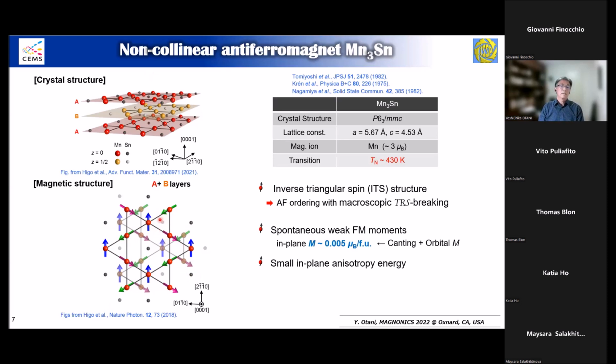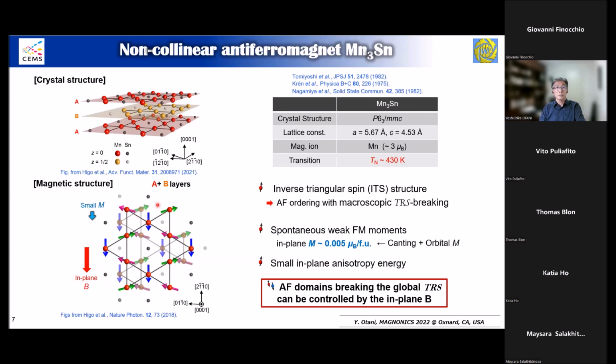If you look at only one set of spins in this region, the time reversal symmetry is broken. When you apply a magnetic field, this spin is slightly tilted, which creates an extremely small, vanishingly small magnetization, so that you can manipulate this spin structure by applying an external field like this. If you flip the magnetic field direction, then you can flip it. So that means, in principle, this so-called octupole behaves like a macro spin. That's a very important message.